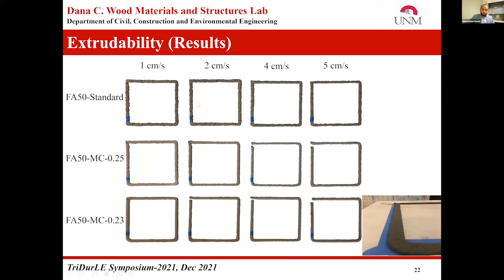This is clear here. We also investigated the effect of printing speed: what is the effect on the extrudability of the printed filament if we increase it from 1 centimeter per second to 5 centimeters per second? We can see that if we increase the printing speed, the dimension of the printed filament kept decreasing in terms of width and thickness. Similarly, the water binder ratio also has an effect on the printing quality, and you can see the dimension conformity, consistency, and surface quality of the filament were significantly improved with the addition of viscosity modifying admixtures.